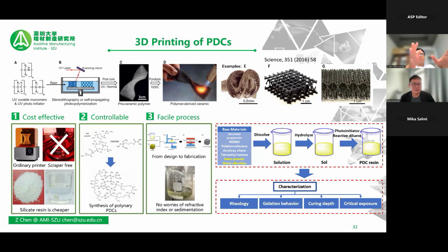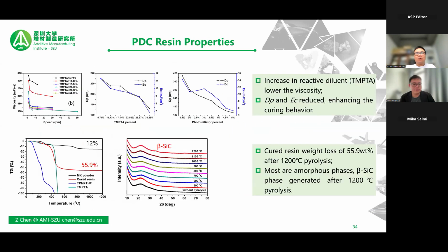Of course, the only additional step is using the high temperature pyrolysis. Well, it's the same as sintering, but the temperature is slightly lower. We call it pyrolysis because the whole process is more of a chemical reaction compared to the normal sintering stage. And we produce our own recipes. This is more chemistry, and we try to see the viscosity, the depth of penetration, and also curing behaviors, all sorts of things. And then we measure the pyrolysis performance as well. And finally, we can produce very good, refined features using this method.